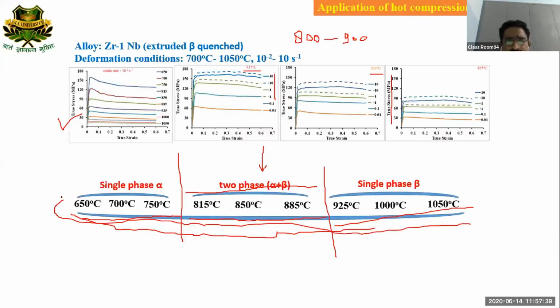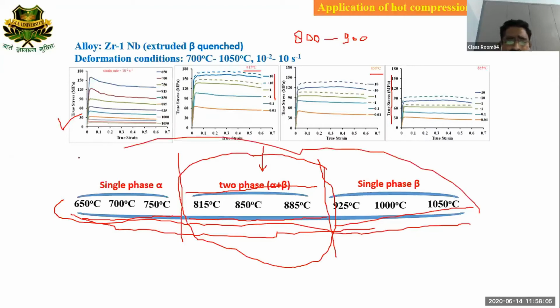I am not bothering about the phases. And one I am developing only with the data of the two-phase region, where only alpha phase and beta phase exist. Why am I doing so? Because every phase has its own nature of deformation. Alpha phase is a hard phase, beta phase is a soft phase. If we cover all the phases in a single constitutive equation, then we cannot understand which phase is dominating or playing the main role during the deformation. So I am going to consider two things: one is the whole parameter set, the other is only the two-phase region.